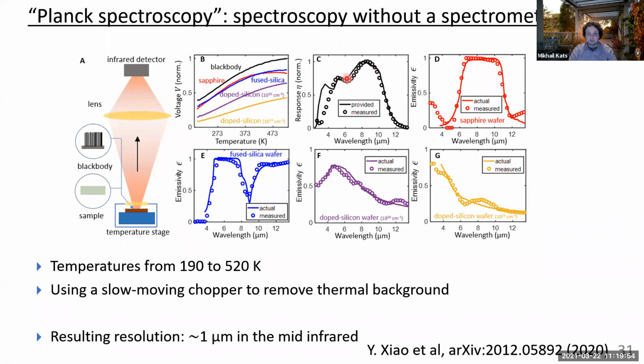And so what we get in the symbols is the extraction algorithm. After the extraction algorithm was applied, this is the spectrum that we measure. And then the solid line, which we call provided, is essentially the responsivity spectrum of the detector provided to us by the vendor. So we just looked at the spec sheet, multiplied by the transmission of the lens from the vendor, multiplied by the transmission of the window from the vendor. And you can see that they overlap very well, I think. So I was very happy that this Planck spectroscopy technique is in fact able to capture the responsivity of the detector. And after we did that, we then used this responsivity of the detector together with this experimental data for all of these other samples, and we inverted to obtain their emissivity spectra.